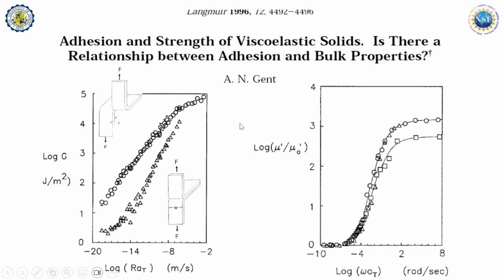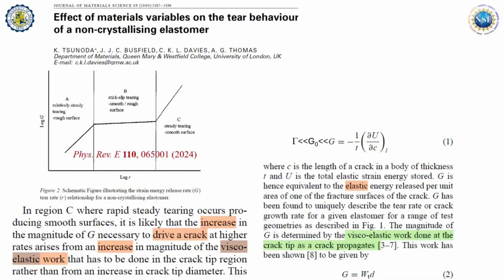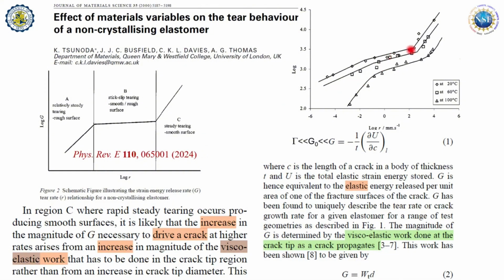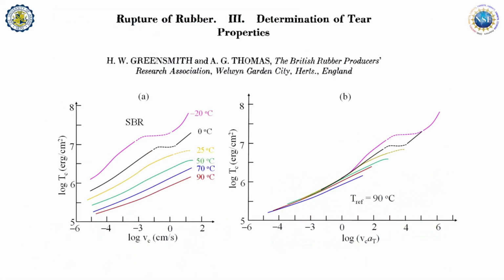In fact, my dear friend Jan worked on this and showed that maybe we can correlate that with linear viscoelasticity. And subsequently, there are papers that summarize the more complicated cases where you can make a transition. And our new theory actually guided us to think about how to depict this transition. So this is one of the publications that I have no time to talk about. Most importantly, they show such relationship between the resistance to fracture versus the rate you use to fracture at different temperatures. You can see these curves are of different shapes, so horizontal shift will not collapse them. For example, take that 70 degree data, they don't collapse.